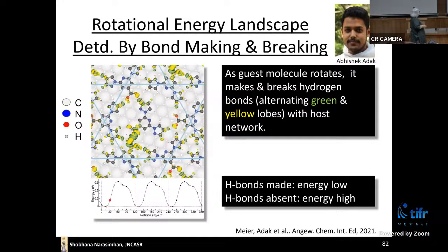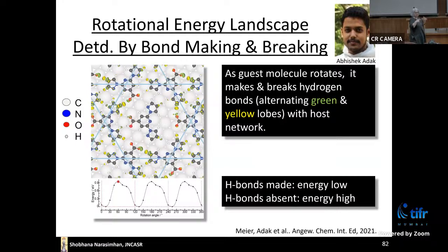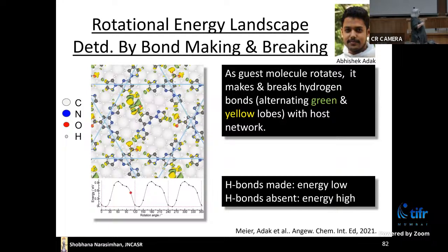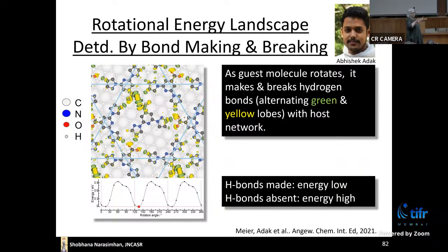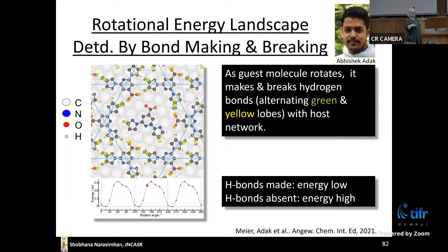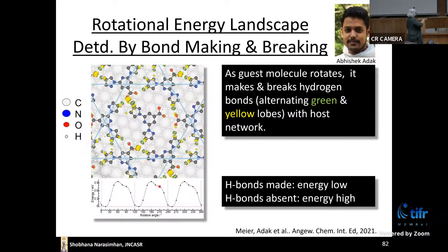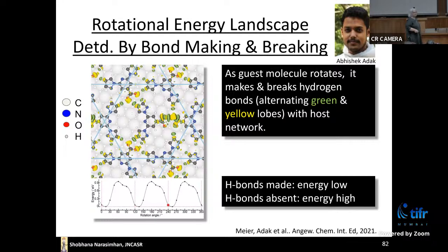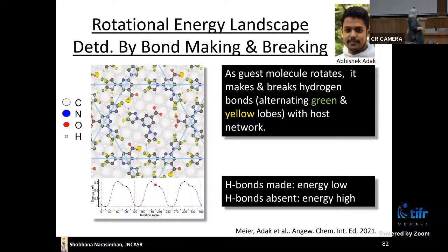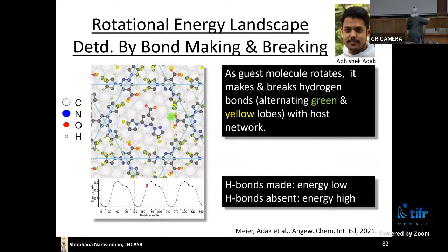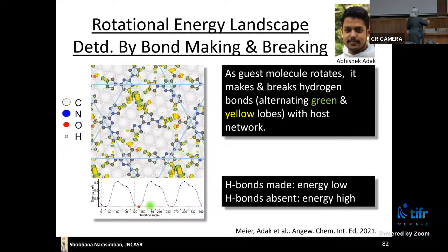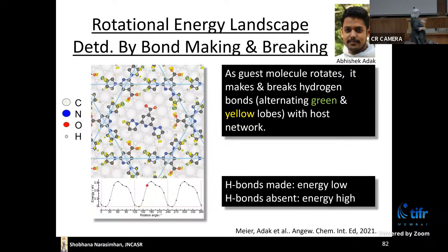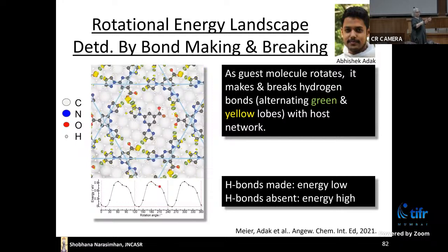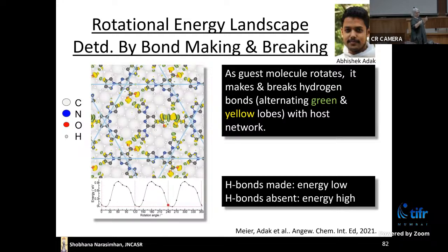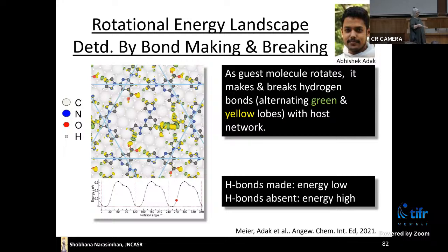Okay, so this is my student Abhishek, and what is there is his theoretical simulation obtained from DFT. So he has the same molecules, and what is in yellow and green are again electron gain and electron loss. And when you have one of these lines of alternating yellow and green, that is a hydrogen bond formed between the central rotor and the cage it's rotating in. And here, what is shown is that as the position changes, he can compute the energy of the system. Okay, and what we find is that when there are a lot of these hydrogen bonds, the energy is low. And when there are very few of these hydrogen bonds, the energy is high. Okay, this seems very obvious, but it was the first time someone had shown it.